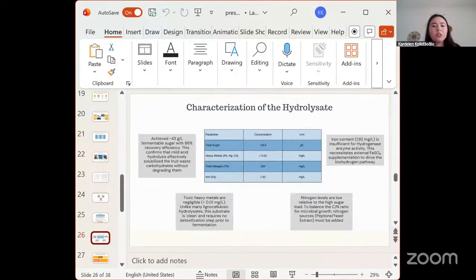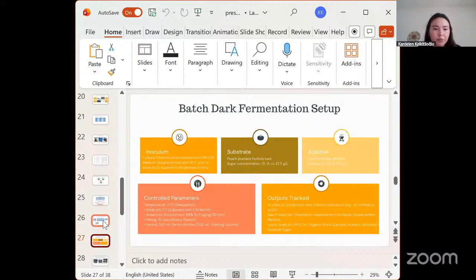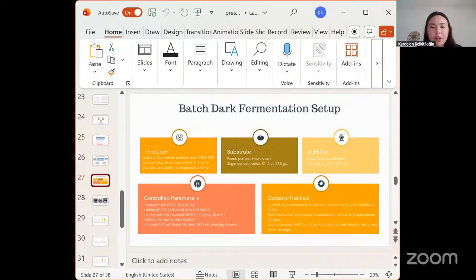The 43 grams per liter hydrolysate showed no toxic heavy metals. However, iron and nitrogen levels were below the threshold for optimal hydrogenase activity. With both our biochar and sugar ready, we proceed to the final stage. We conducted batch fermentation tests using Clostridium pasteurianum.